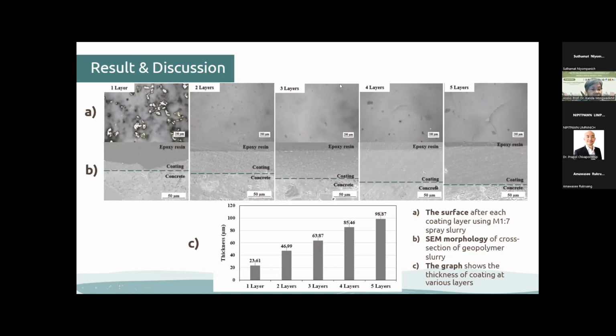After the fourth coating, a few wrinkles showed, but we observed that the coating layer had no cracks on the surface. After the fifth coating, obvious cracks were observed. The porosity of the geopolymer coating layer is shown in this cross section to show the average thickness, and the bond interface between the geopolymer slurry and the substrate was compact and tightly bonded. The graph shows the thickness of the coating at various layers.